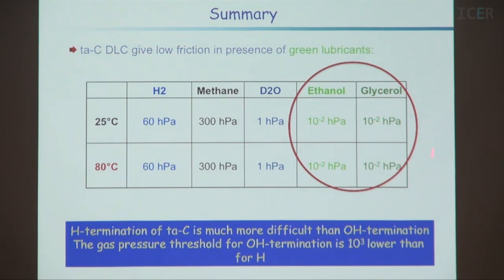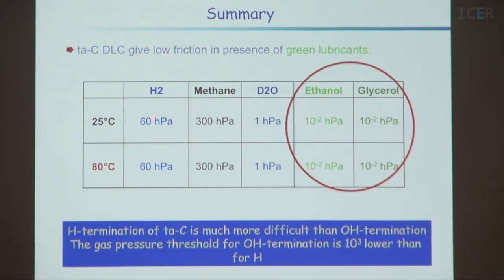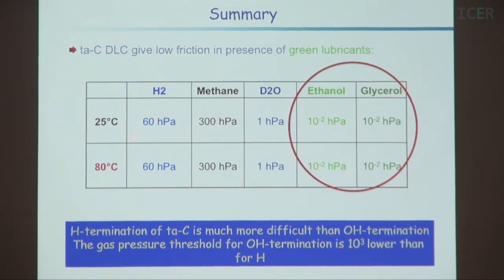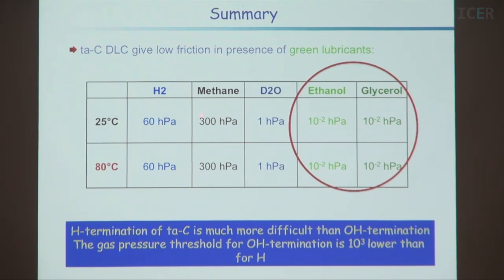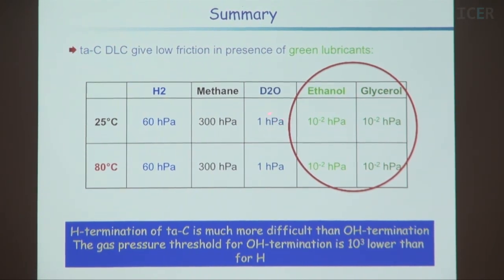So, to summarize, you can see that hydrogen reacts and lubricates, but high concentrations are necessary. For methane, even high concentrations are needed. But for water, a small concentration, and for these two alcohol molecules, very low concentrations are sufficient to lubricate the carbon.